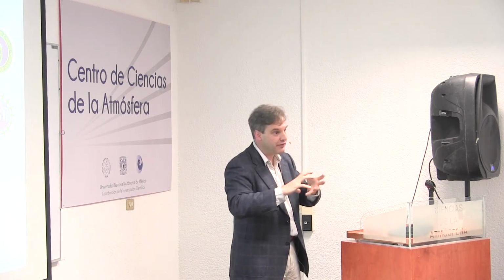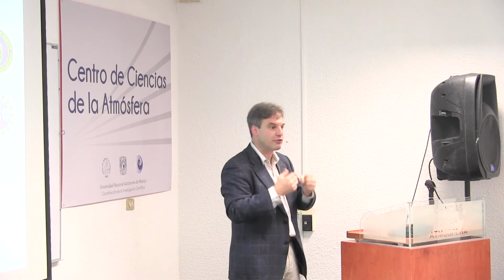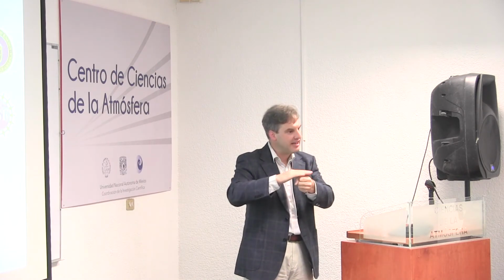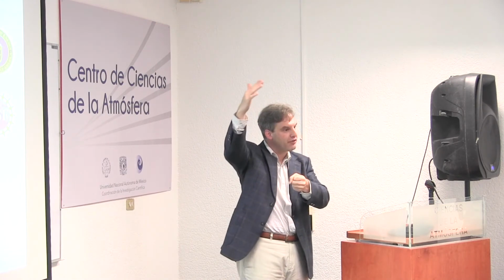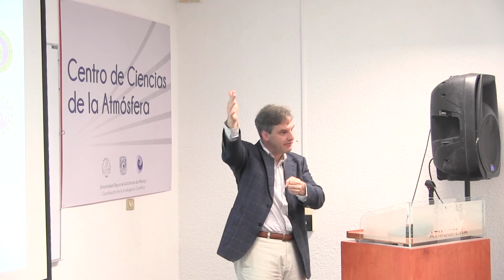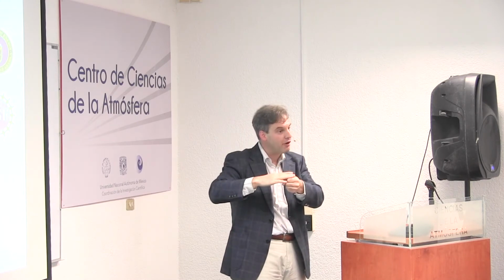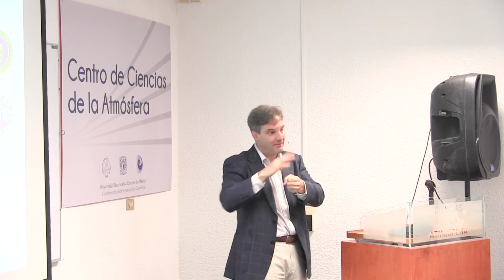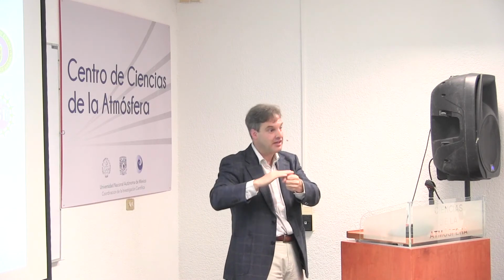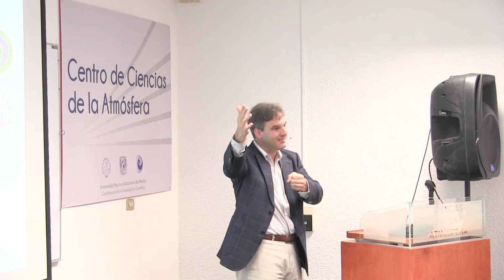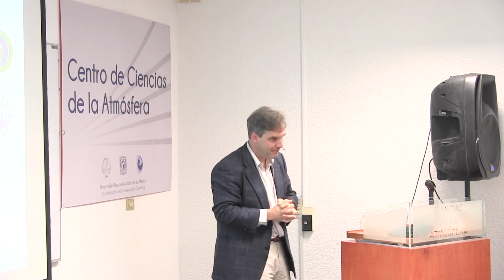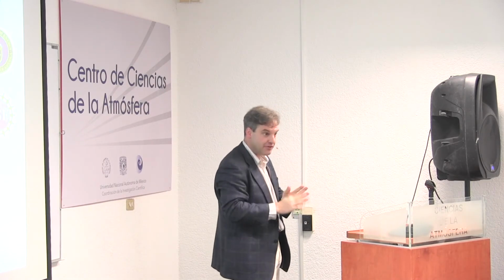Therefore we need to know the composition as well. So I can tell you, if it's more hydrophobic or less hygroscopic, it will take longer to undergo this amorphous phase transition into the liquid phase. Whereas if it's more hygroscopic - we don't have much measurements on that - it will deliquesce quicker. Even at fixed temperature, just with humidity.